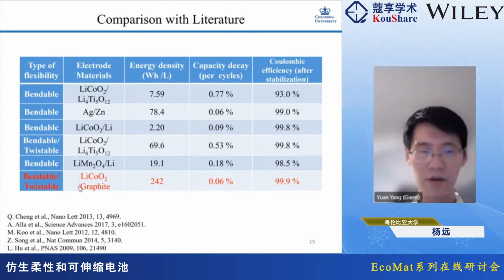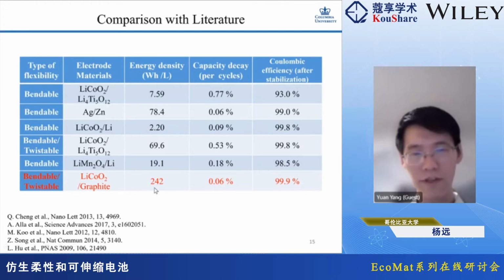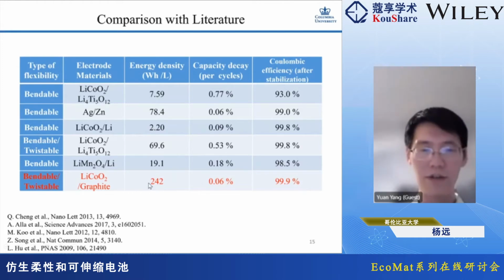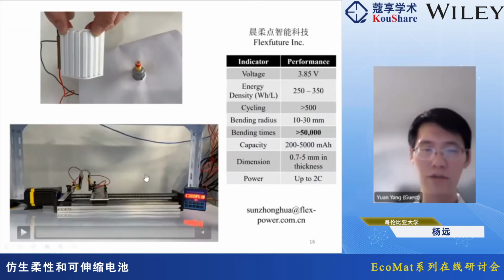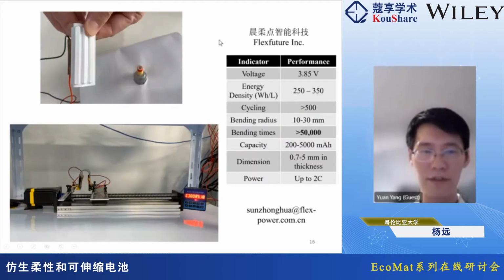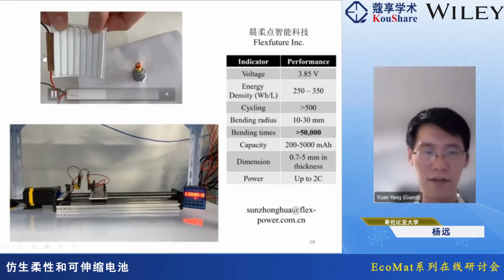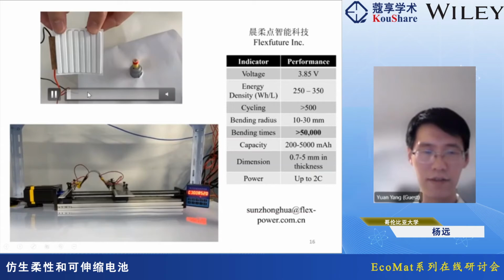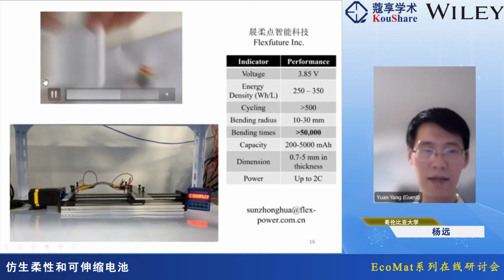Compared with the literature, I think the advantage of this structure is that it not only has a good cycling life, but the energy density is also attractive. 240 is not a very high value actually. That's because in our lab demonstration, the mass loading of the active material is about 1 milligram per square centimeter. If we push it further to 3 milligrams per square centimeter, as in standard commercial lithium-ion batteries, I think this number can be improved. And currently, we are also trying to commercialize it. We collaborate with a company to make standard cells, and you can see a cell prepared by the company.